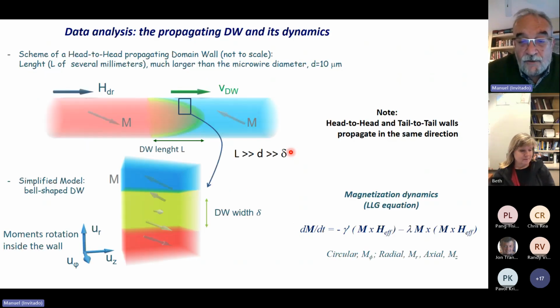Okay, so we developed recently a simple model to study the dynamics of the domain wall. Here you see this is the domain wall. We have chosen a parabolic shape, and the magnetization in the domains is not perfectly axial, but because of the experiments, we know that it has some helical component. So it is important to say that the length of the domain wall is much larger than the diameter. It is not to scale. And the diameter of the wire is also much larger than the thickness of the domain wall, which is shown schematically here.